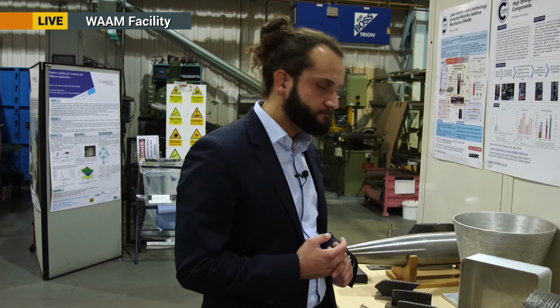But of course, in our case, digital technologies, for example, laser scanning and other metrology methods help us, because we can deposit the material, take a nice scan of it in a quick and inexpensive way, and then we know exactly how to set up that part on the machining center. And of course, between one and the other, typically we would have to resort to a stress relieving heat treatment to reduce the residual stress and the internal tension, but these are established processes that have been around for decades.